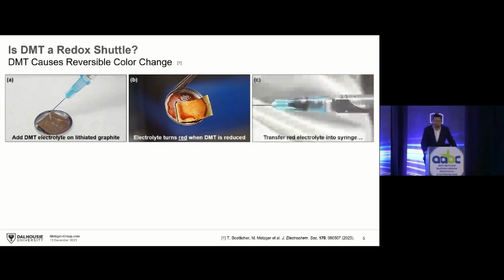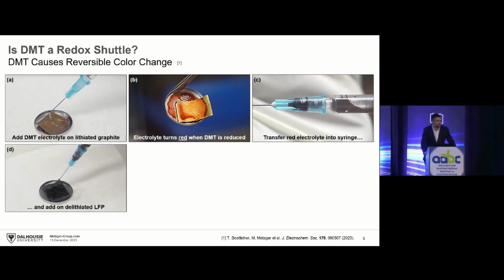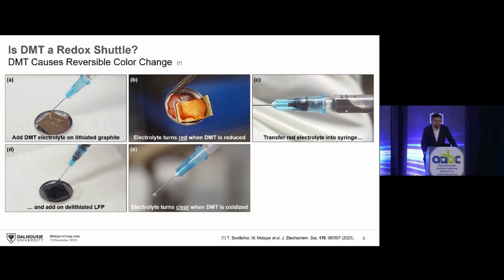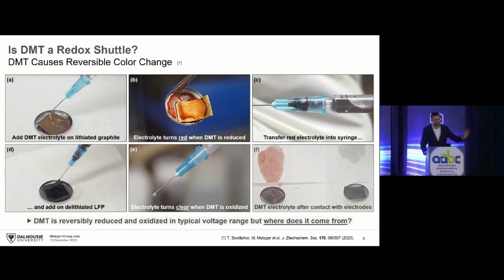Now we can take that red electrolyte back into our syringe and put it on a delithiated LFP electrode, an LFP electrode which is at a high voltage, 3.65 volts. And when you do that, the electrolyte turns transparent again. So it's truly a reversible color change we're seeing here. This is the electrolyte after it has been in touch with the negative and the positive electrode. So the DMT molecule undergoes a reversible redox reaction. When it's reduced at the negative electrode, it turns red. And when it's in contact with the positive electrode, it becomes transparent again. That's characteristic of a redox shuttle molecule.